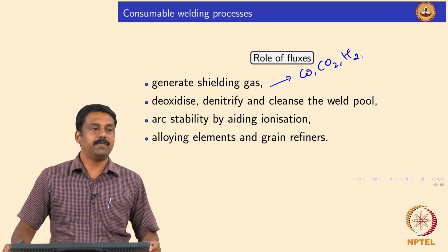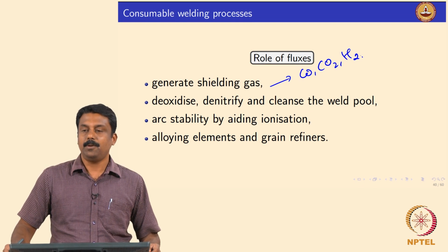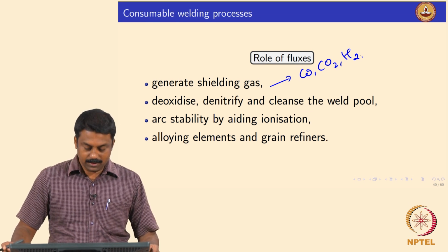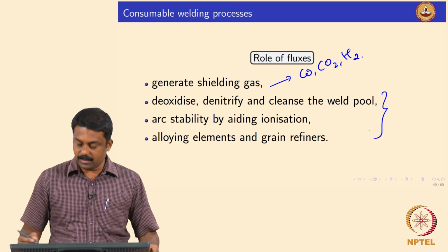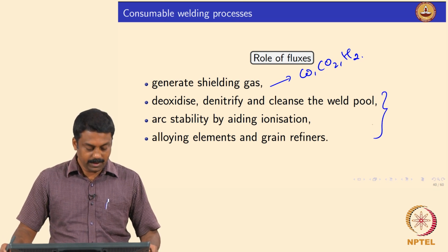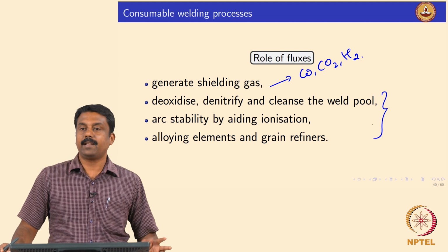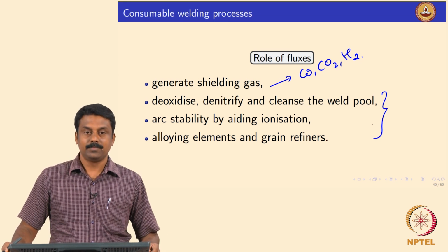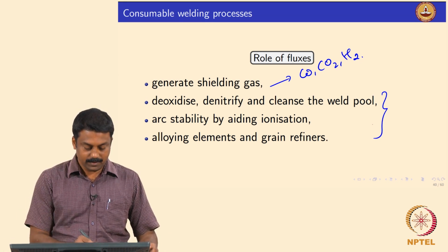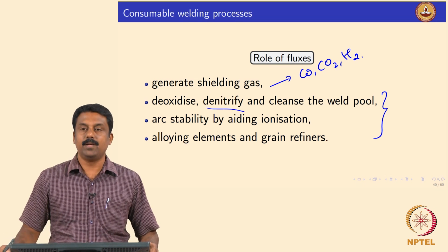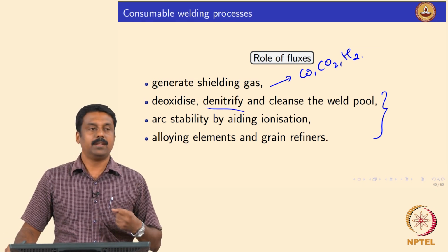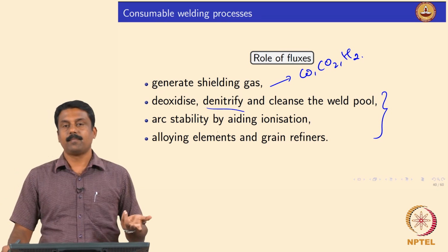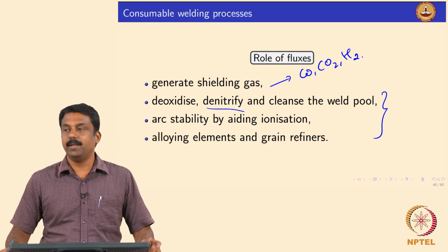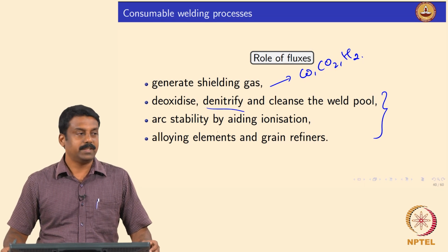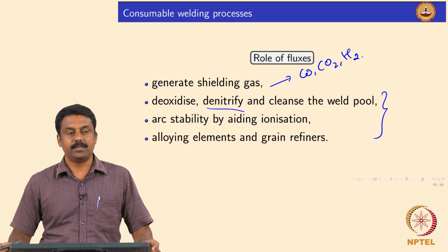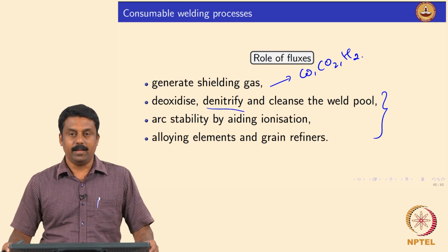So, that is the main function, to generate shielding gas, and apart from this there are some secondary functions these fluxes do. They act as a deoxidizer for the weld pool, and they also denitrify and clean the weld pool, and you can also have dephosphorization and desulfurization done by adding elements which promote deoxidization, denitrization, desulfurization or dephosphorization. So, to clean the weld pool,